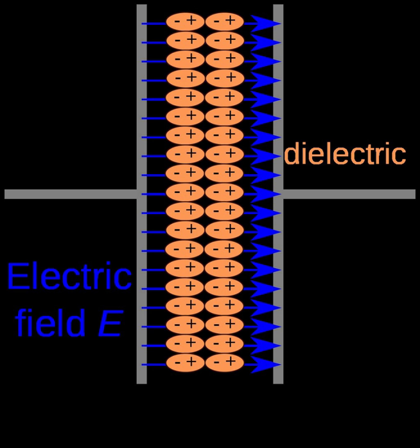This is one instance of a general phenomenon known as material dispersion, a frequency-dependent response of a medium for wave propagation. When the frequency becomes higher, dipolar polarization can no longer follow the oscillations of the electric field in the microwave region around 10^10 Hz. Ionic polarization and molecular distortion polarization can no longer track the electric field past the infrared or far infrared region around 10^13 Hz. Electronic polarization loses its response in the ultraviolet region around 10^15 Hz.